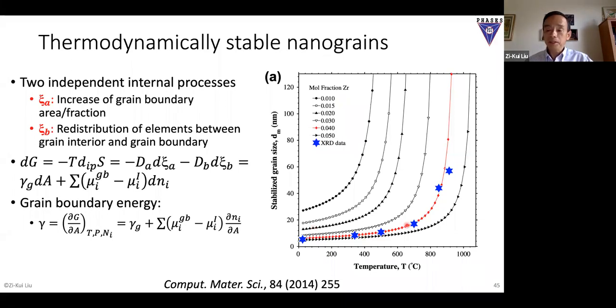It's pretty good. Of course the model always has parameters - we need to do some dynamic modeling of the grain boundary, some dynamic modeling of the grains, and this is the BCC phase. We had it already, but we need the grain boundary modeling. So we did some work modeling there, and we can predict it.